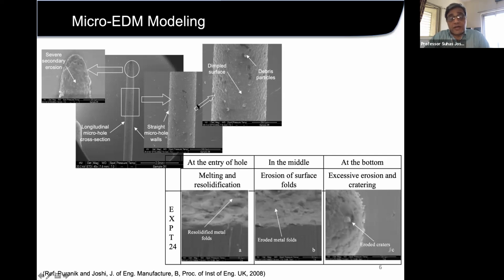But you can see that there is a very nicely dimpled structure on the surfaces. That means the EDM process is really happening well. But when it goes down here towards the tip, you find that this is a completely botched up surface, in the sense that sparking and resparking happens on this. So this is a very close view of the surface, which is at the entry of the hole.